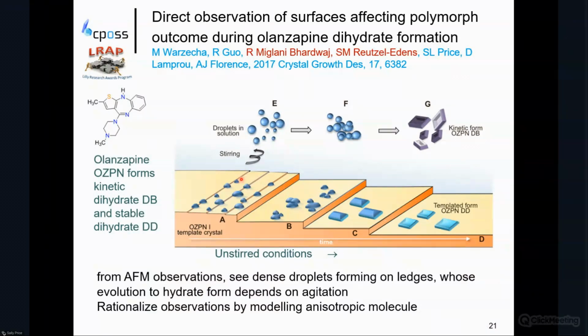Whereas when there was any stirring, which is of course what you usually get when you're trying to dissolve olanzapine, the hillocks became droplets and solutions which crystallized to the dihydrate again, but the kinetic form B. So we had the challenge of rationalizing what's going on here. Why is the surface having this effect?